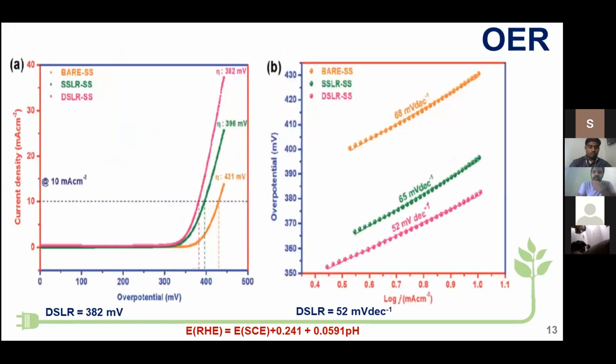This slide shows the OER, oxygen evolution reaction, of the as-fabricated electrodes. Figure A shows the linear sweep voltammetry curves of bare, single side and double side laser irradiated stainless steel. So it's one kind of fuel cell reaction, as Dr. Gaudaman said in the earlier presentation. The minimum output is about 10 milliampere, and all three electrodes achieved that. But among these three, the double side laser irradiated stainless steel achieved a very low overpotential of about 382 millivolt.